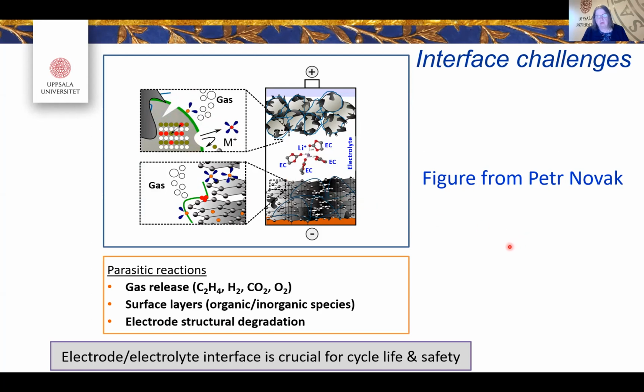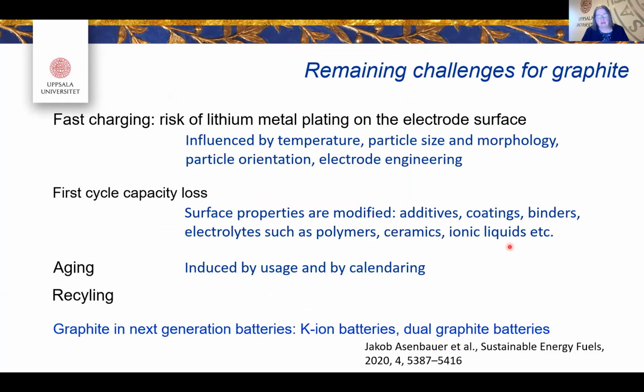So with all these components in mind, we still see the remaining challenges for graphite, for instance. Fast charging, the risk of lithium plating, influenced by temperature, particle size, morphology, particle orientation, electrode engineering. We still don't really control it in a comprehensive way. It's interesting, though, that there are so many studies on it. We have the first cycle capacity loss. This is an expensive thing for industry.